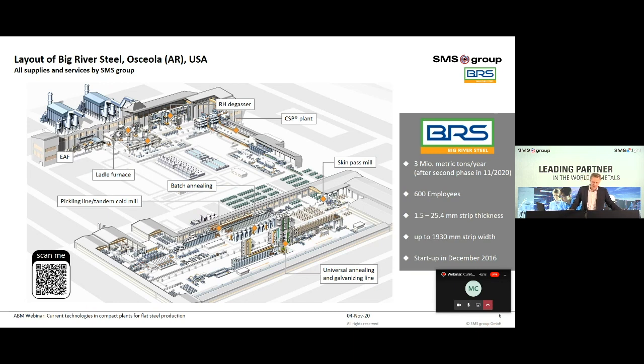The entire process equipment, including the environmental equipment and the electric automation, was delivered by SMS Group. As said, Big River Steel will produce 3 million metric tons per year after commissioning of the second phase, with only 600 employees in total. The hot strip thickness range is 1.5 millimeter up to 25.4 millimeter, and Big River is able to produce strips up to 1930 millimeter width.